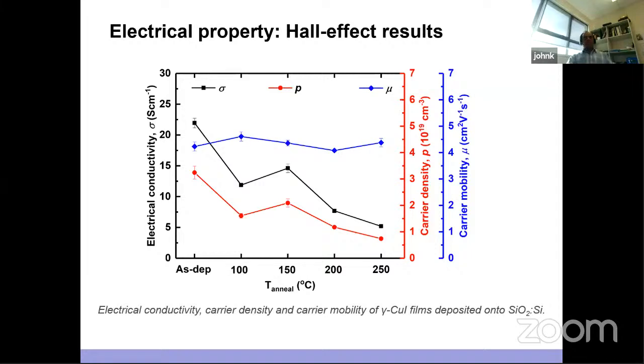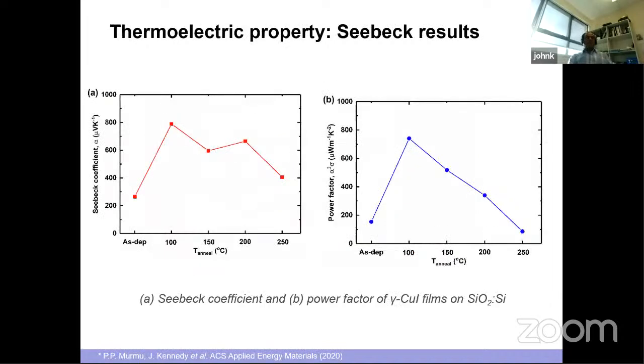And it's a p-type conductivity because copper vacancies are the main source of holes here. Because of the slight imbalance in the stoichiometry after annealing, you can see that decrease. But the electrical conductivity is also decreased significantly. So it's interesting to see how this thing changes by simply annealing at a low temperature.